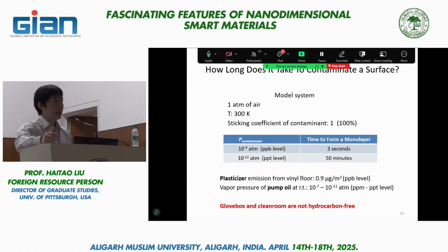Translate that to concentration at atmospheric pressure, and that would be a ppb level, parts per billion. If you are working at a parts per trillion level, that will make it about an hour. So not too far away from what we saw in our kinetic study. If you go back to the data on the left-hand side, that's about 20-30 minutes in the near term, and for a day that's 24 hours. So order of magnitude-wise, we're within that kind of range.